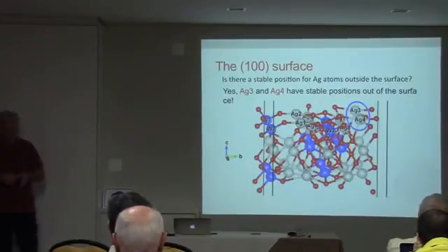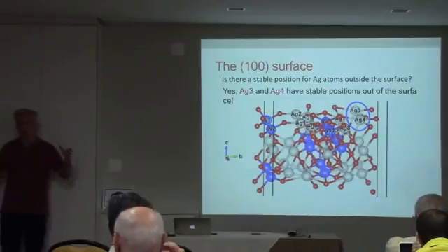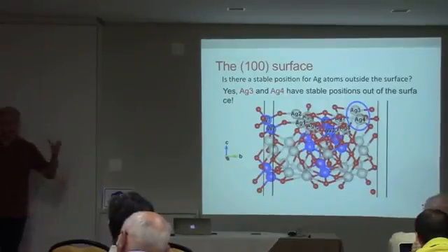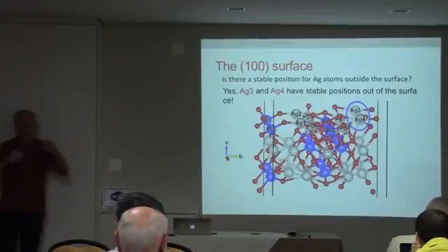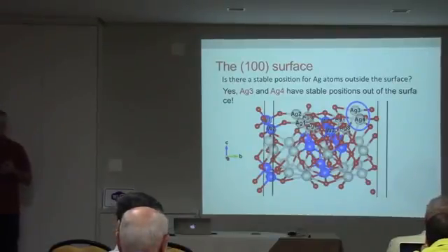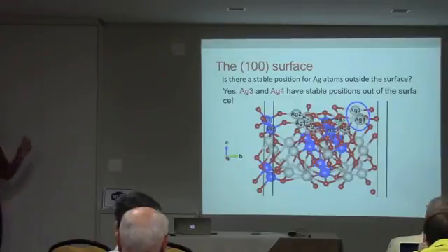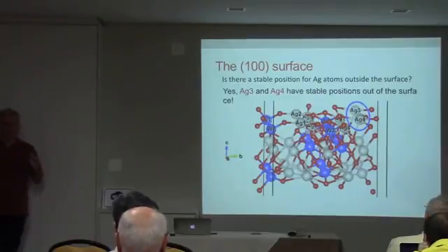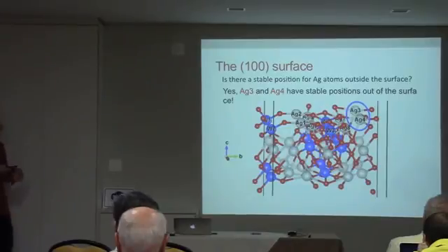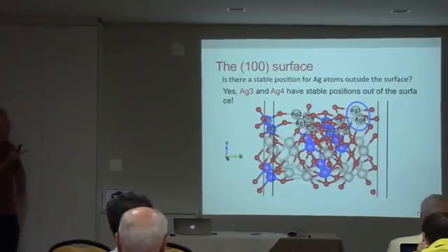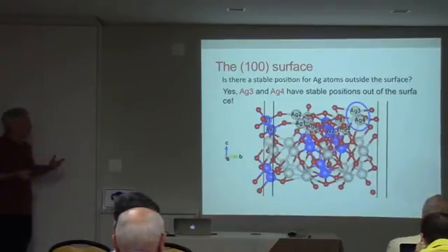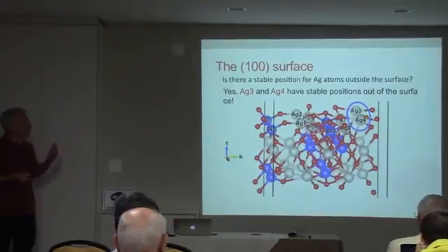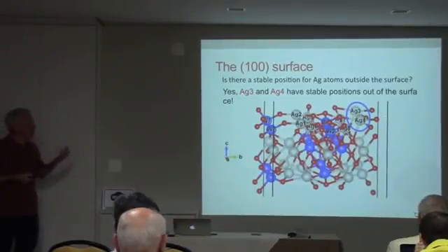Experimentally, we find the formation of large metallic silver structures, and the substrate still keeps a silver tungstate structure, very crystalline. So this result is interesting because it shows that not all of the silver atoms can initiate the process.